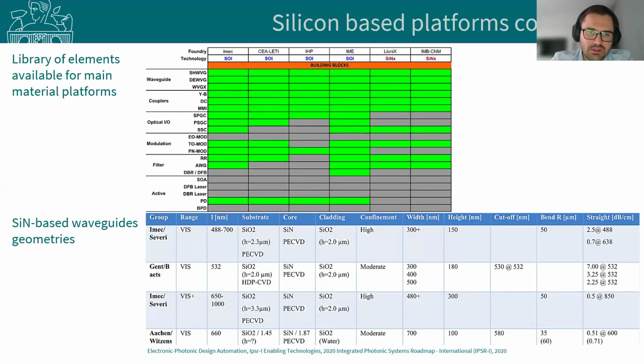With silicon nitride and generally in silicon, you can see the comparison of dimensions of these elements. What I want to highlight is that all the critical dimensions of these elements are below 1 micron. This leads to some problems in technology, because we cannot use classical standard photolithography. We need to go to more advanced techniques, and the small dimensions also make some additional difficulties in etching.